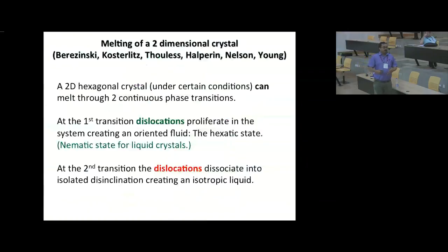Now, when does one see this kind of two-step order disorder transition? The theory that exists is for the melting of a two-dimensional crystal, the celebrated BKT HNY theory, which predicts that under certain conditions a 2D hexagonal crystal can melt through two continuous phase transitions. At the first transition, you have dislocations that proliferate, and at the second transition, this is wrong, you have disclinations. Oh, dislocations dissociate into isolated disclinations, that is correct, and you get an isotropic liquid.